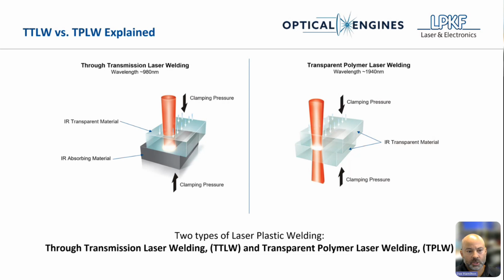So for standard through transmission laser welding, on the left here, we use wavelengths in the range of 980 nanometers, and in some cases fiber lasers in the range of 1,000 nanometers or 1064. There are different variants of the wavelength. One of the joining partners needs to be IR transparent, and the other needs to be IR absorbing. It doesn't have to be clear or black to the eye, but they just need to either pass the IR energy or absorb the IR energy.